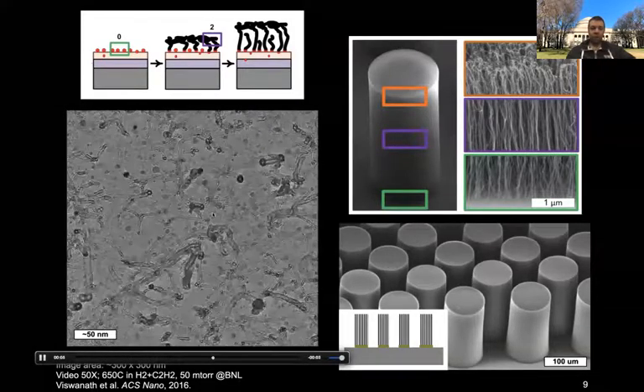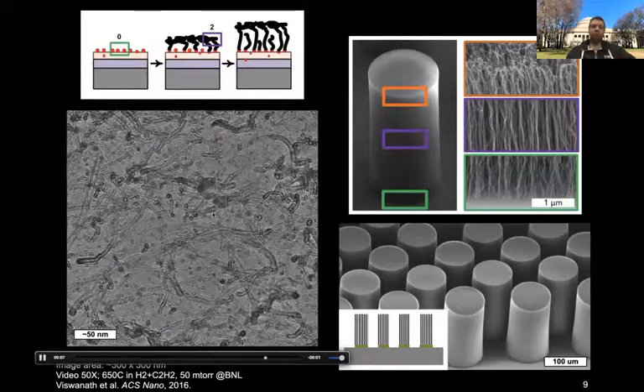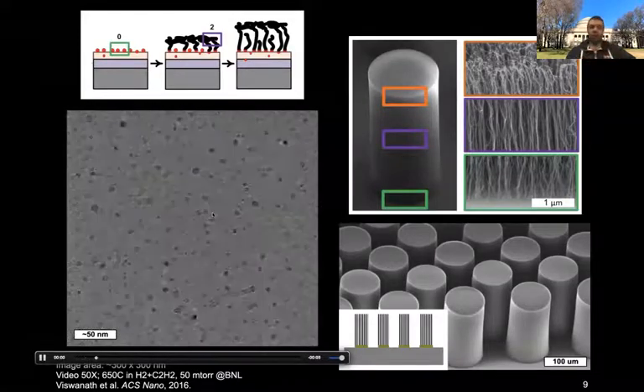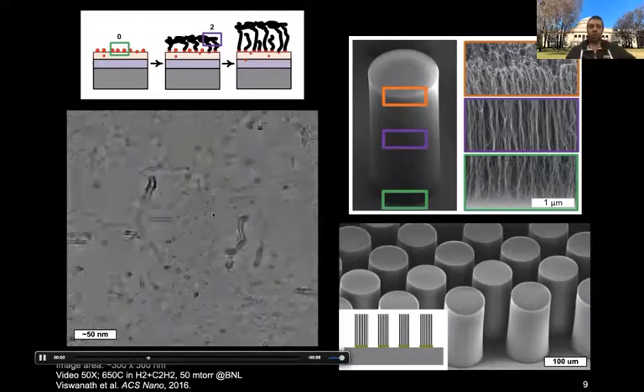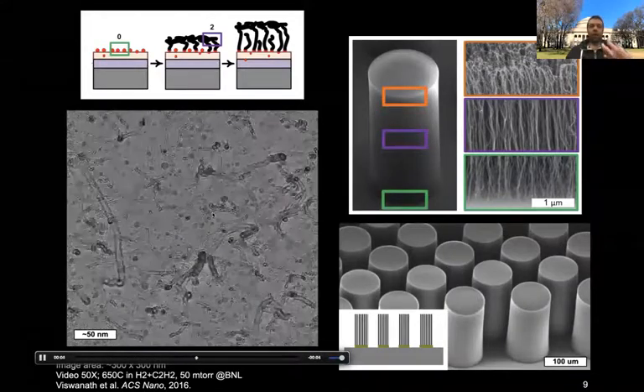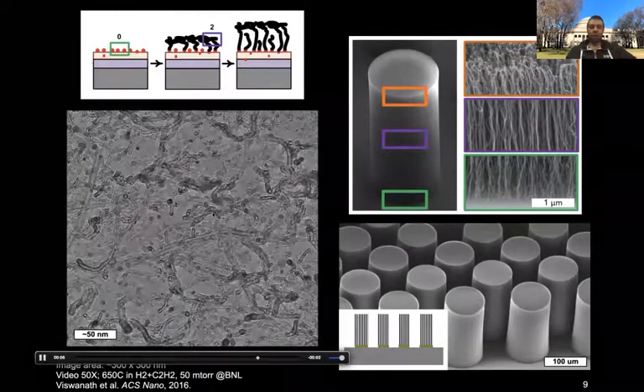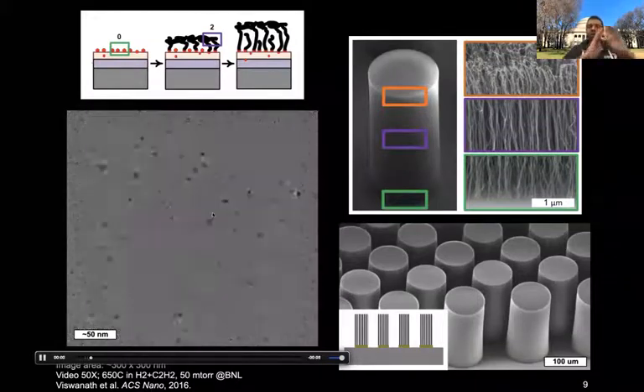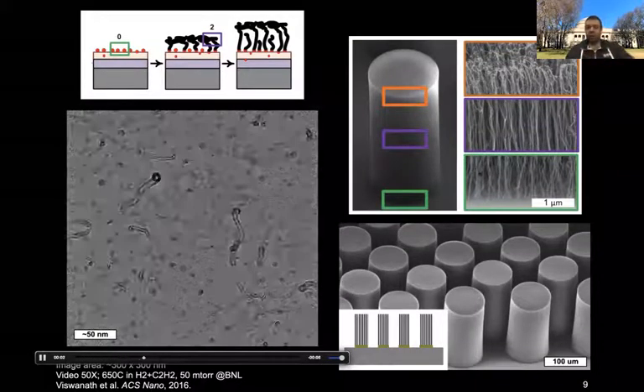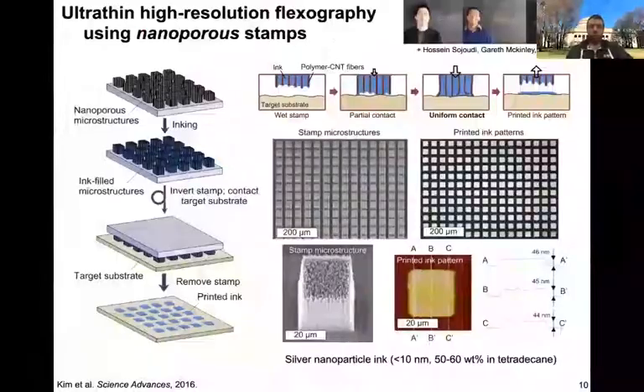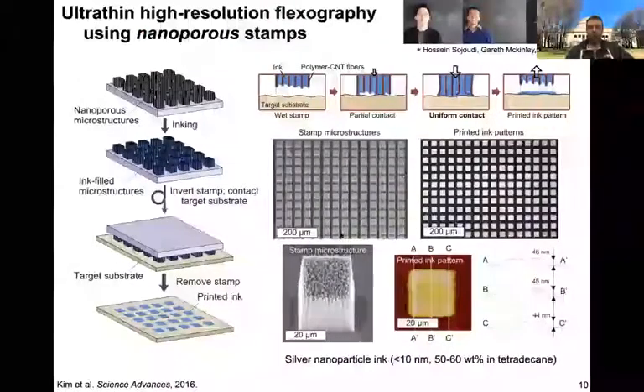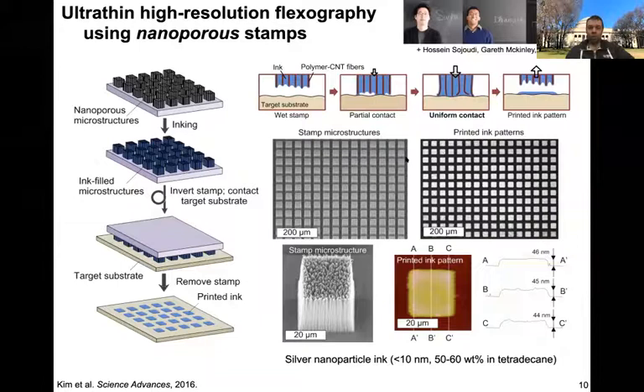And here is some work done about 5 years ago using in situ TEM, environmental TEM, to look at the CNT forest growth process. And here we're looking down at a population of catalyst particles, and it just gives a sense of the self-organization of the CNTs that ultimately leads to the forest.